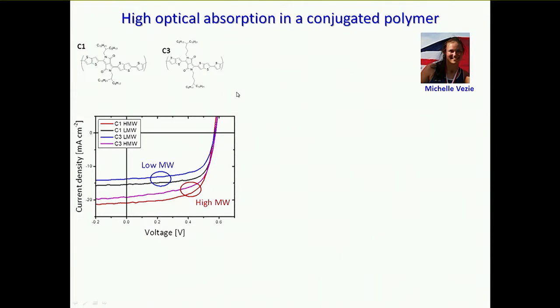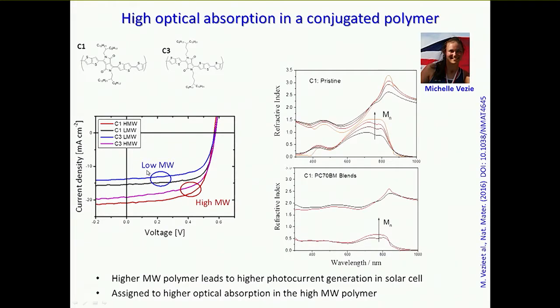But when we looked more carefully, we found actually the difference didn't have anything to do with the side chain, really. It had to do with the molecular weight of the polymer. And what we discovered when we looked more carefully was that the thing that was changing when we changed the molecular weight of the polymer was actually the strength of the optical absorption, not the band gap, but the strength. So if you like, the oscillator strength of the primary transitions seemed to be increasing with molecular weight. And this was something that we found very puzzling.